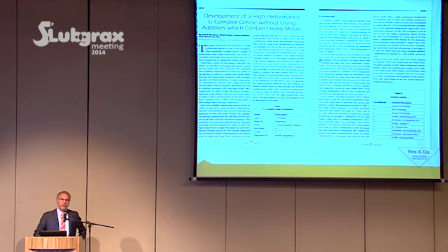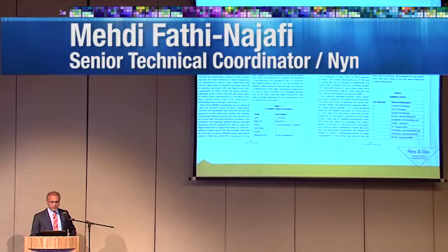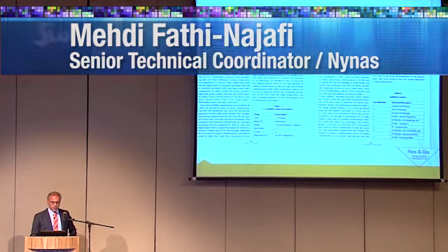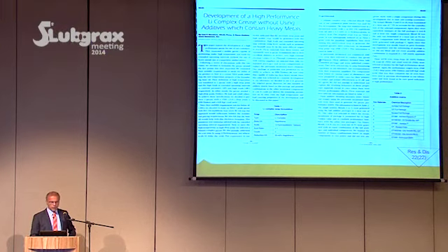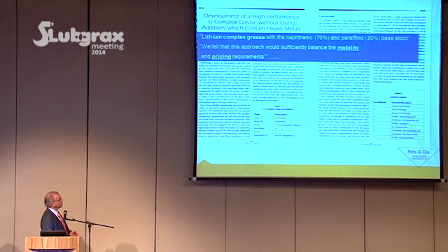Naphthenic oil has been used for ages in the United States and in Western Europe in combination with paraffinic oil. This paper was published some years ago at NLGI US, and I thought it good to refresh some memories if you know it. Otherwise, it highlights that naphthenic oil could be used even for high temperature greases. Here, lithium complex was used. I don't want to test your eyes, so don't try to read it. This is what they concluded. They made lithium greases, and what they were looking for was good mobility and good pricing. They used 70% naphthenic oil and 30% paraffinic, and they got what they were looking for.